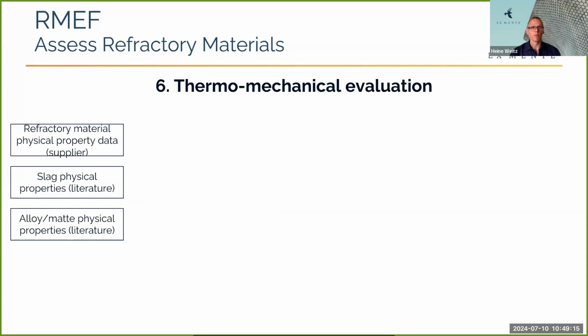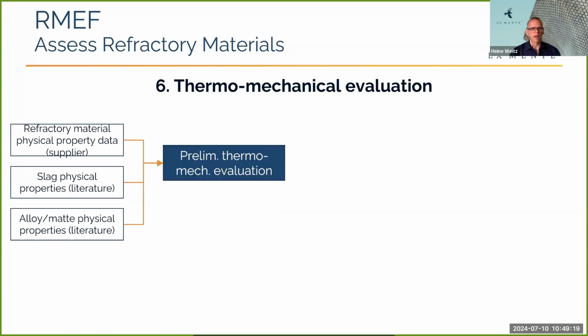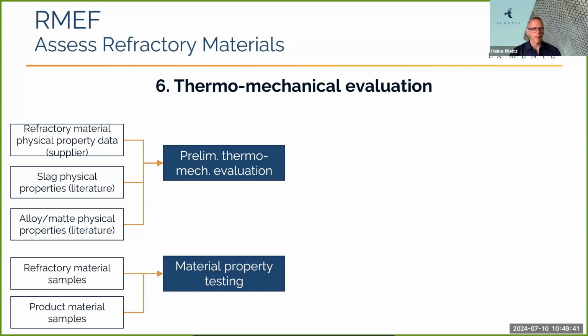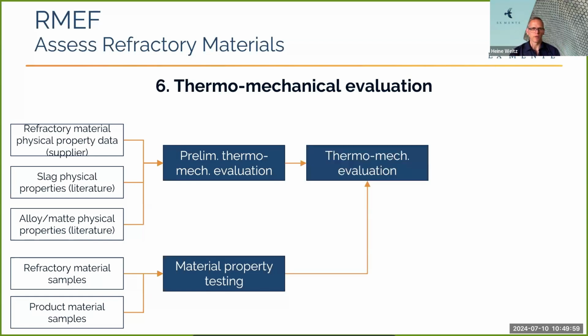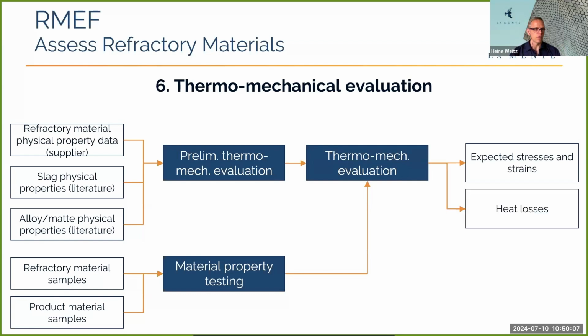Now, for the thermomechanical evaluation, again, we can take the information that we have available at the start: the refractory material physical properties that we get from the supplier, slag physical properties and alloy matte physical properties from literature, and create a multiphysics model to describe the process. But then you can also substantiate that by doing material property testing, taking the refractory materials and the product material samples and actually identifying or narrowing down the range of material properties to feed into the multiphysics model again, to allow us to understand the expected stresses and strains and also the heat losses.